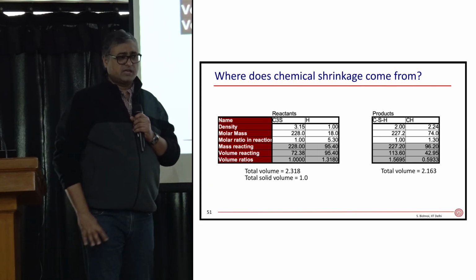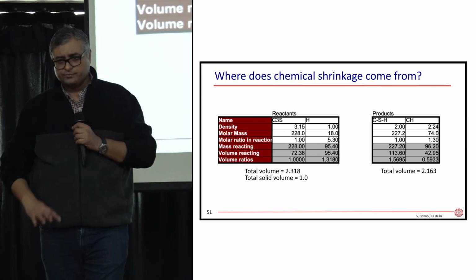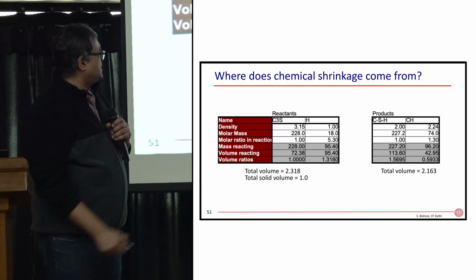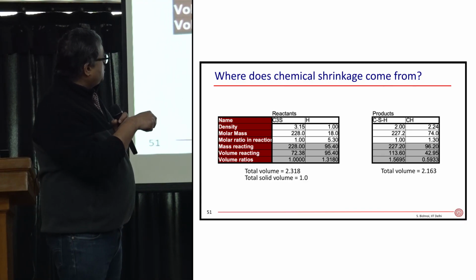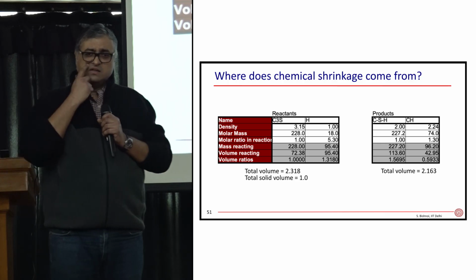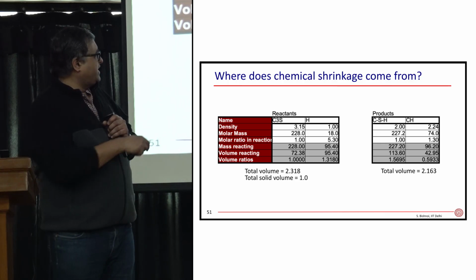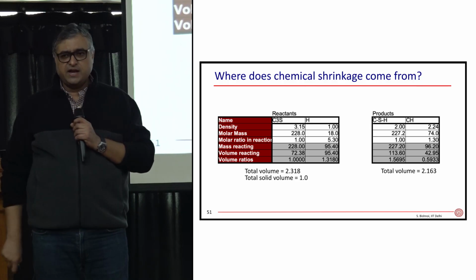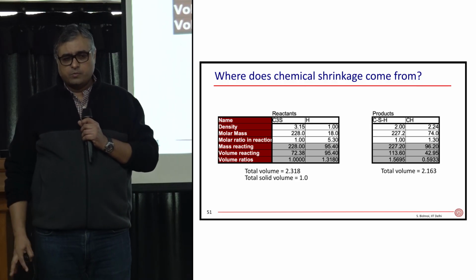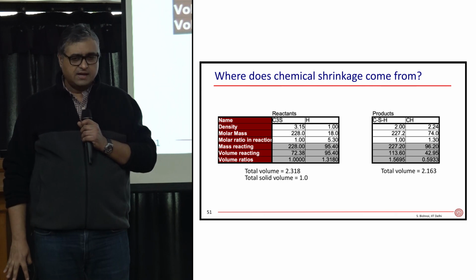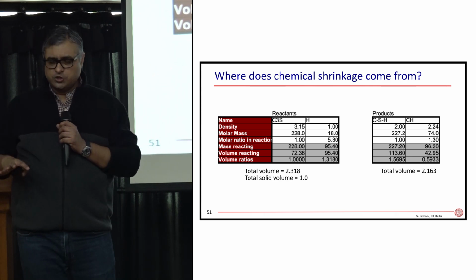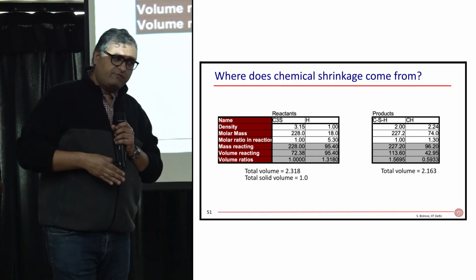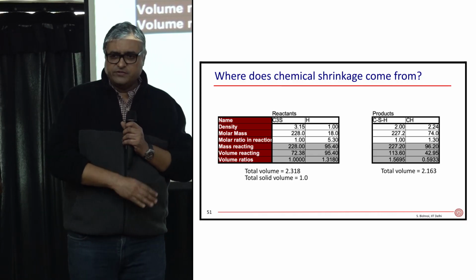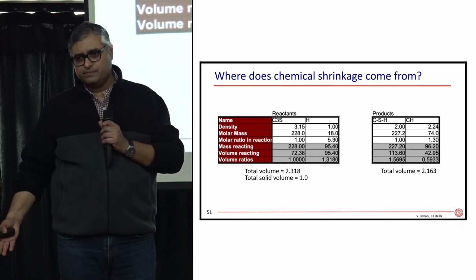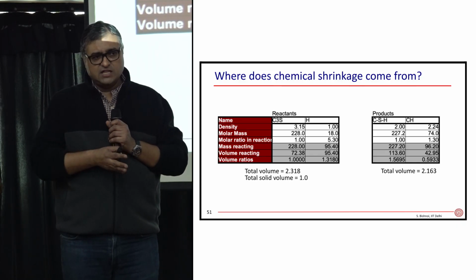Now let's see some more things from these numbers over here. One more thing that you would notice is that if you find out the ratio of this weight of water to the weight of C3S, can you find out what that ratio is? Divide 95.4 by 228, you will get 0.42. At a water binder ratio of around 0.42, you have just enough water to react with all the cement, you have just enough cement to react with all the water. You are at a stoichiometric balance for this reaction.